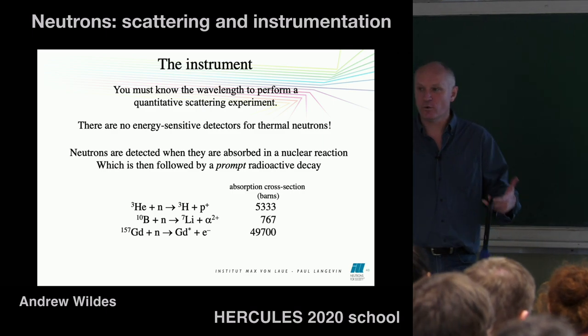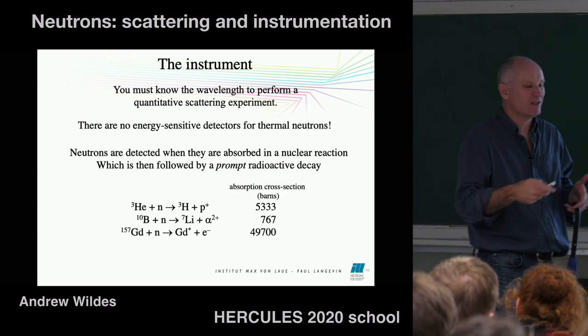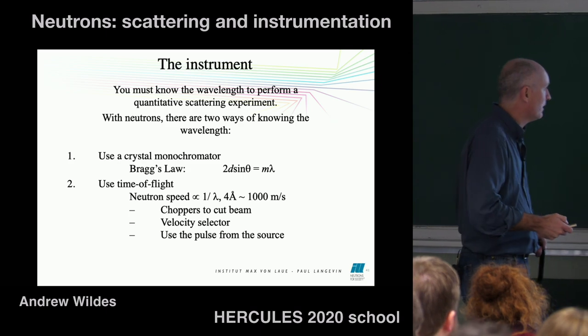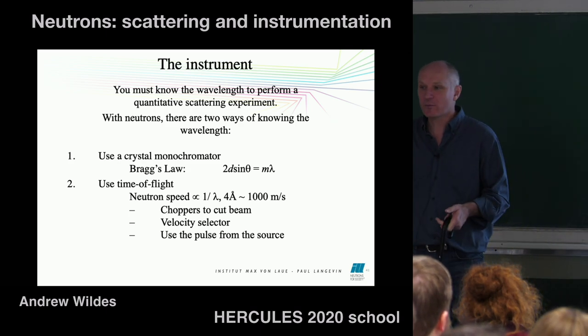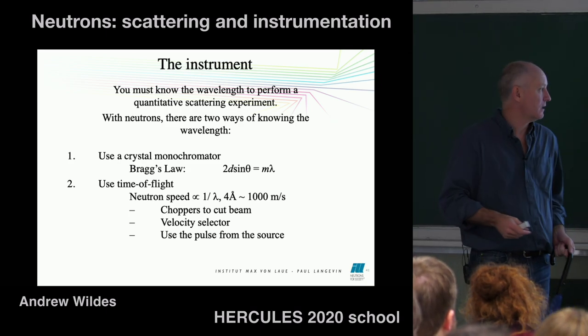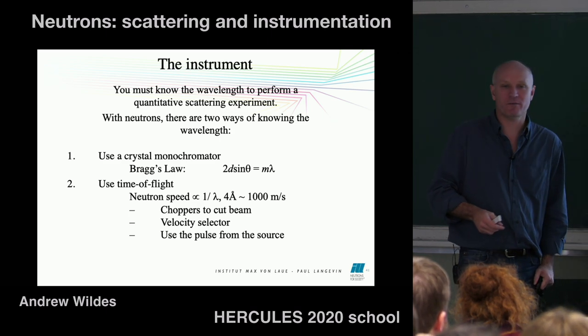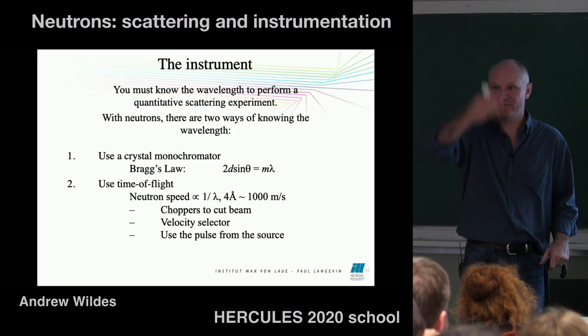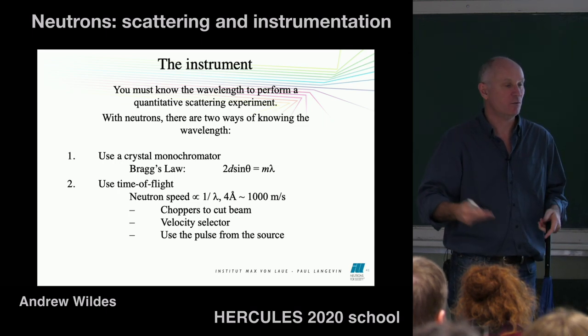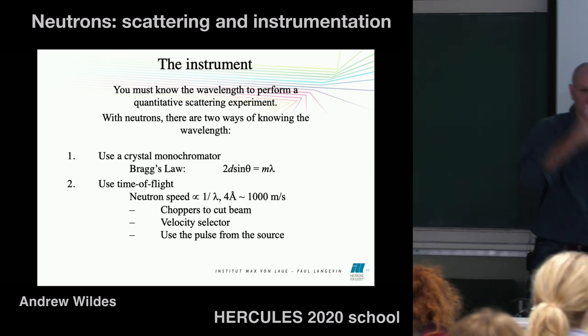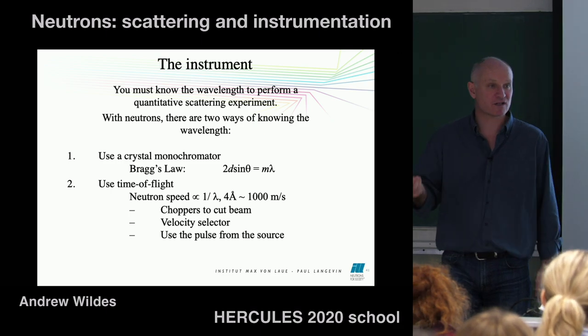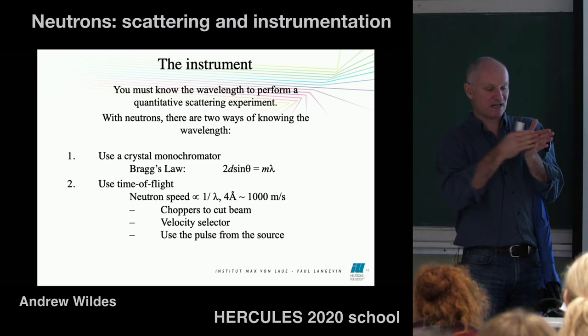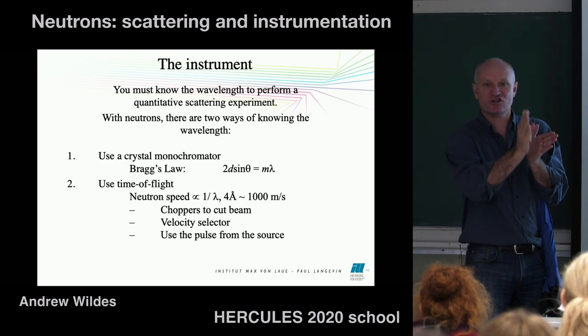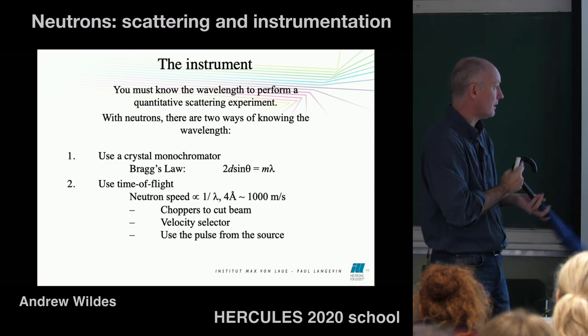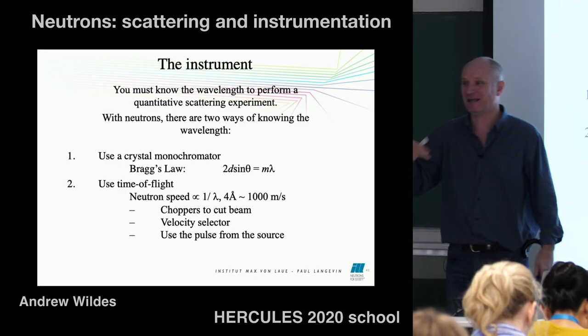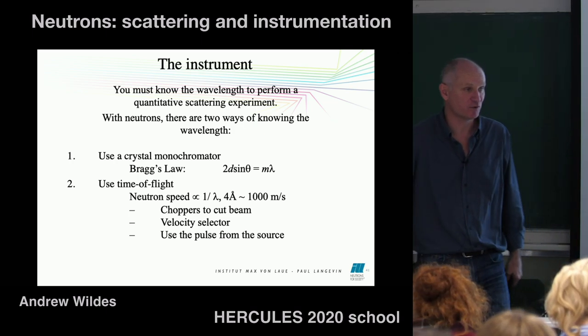Okay, so if you want to know the wavelength for your neutrons, then there's effectively two ways that you can do it. The first one is pretty well known from a bunch of other types of techniques. You can use a crystal monochromator. You get a very well-defined, very nice crystal with very well-defined d-spacing between certain planes, and you use Bragg's law. You have a beam of neutrons coming in, you get your crystal at a certain orientation, and you'll get one wavelength coming out. In fact, you get multiple wavelengths, so you have to be a bit careful. Sometimes you need to filter against these multiple wavelengths.